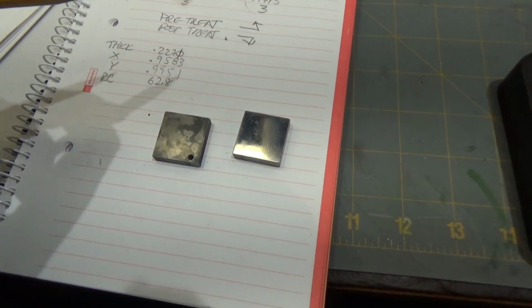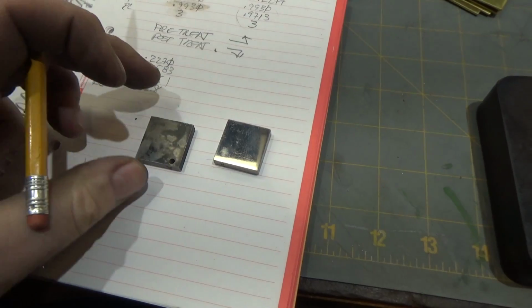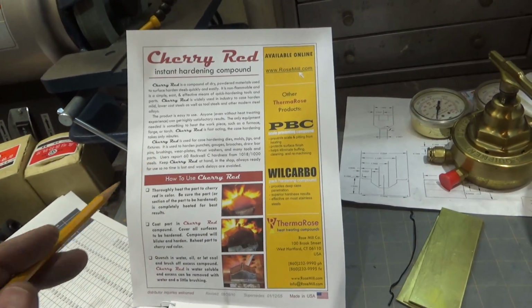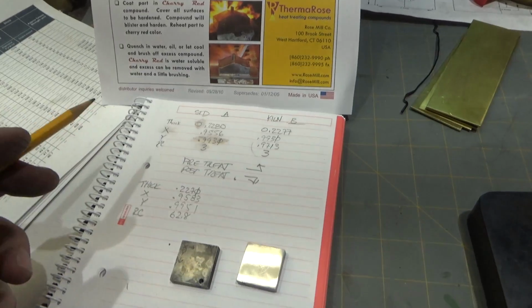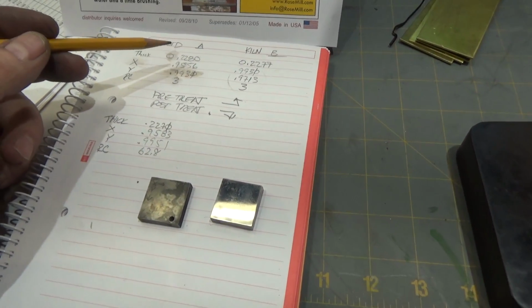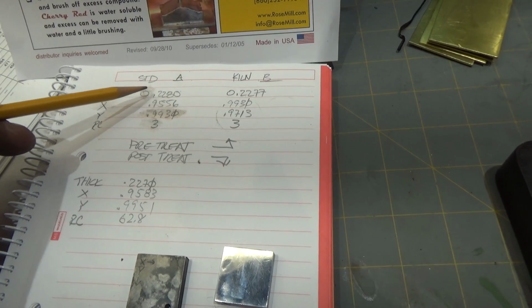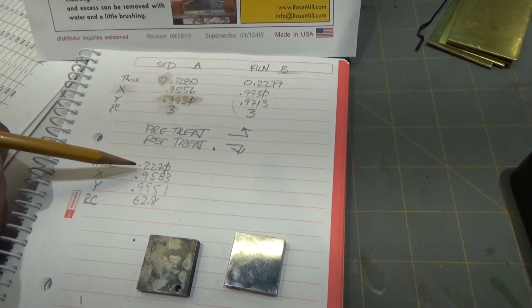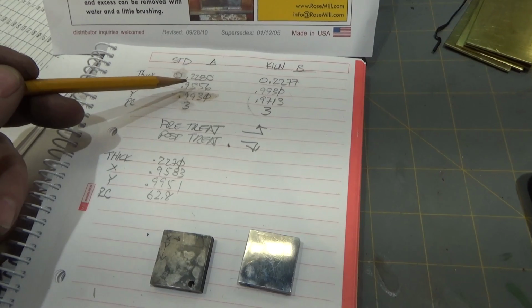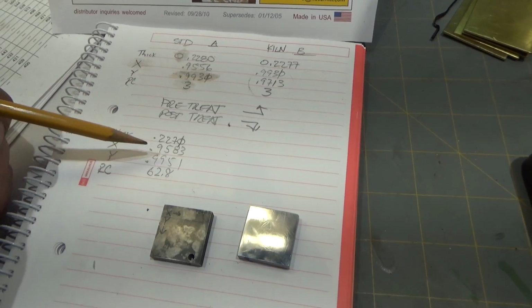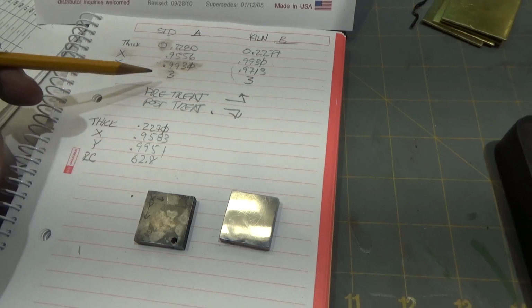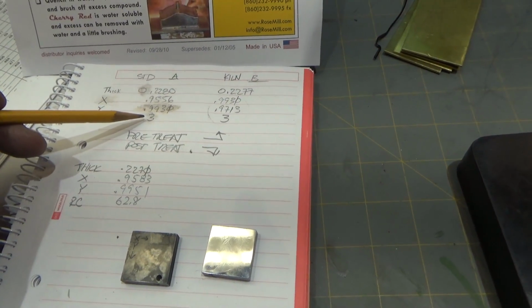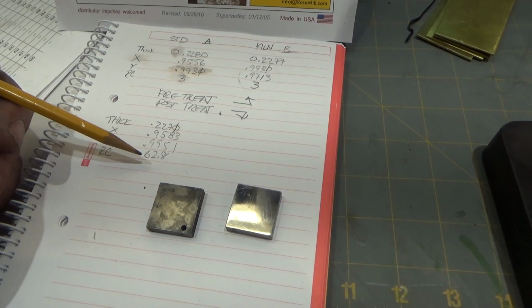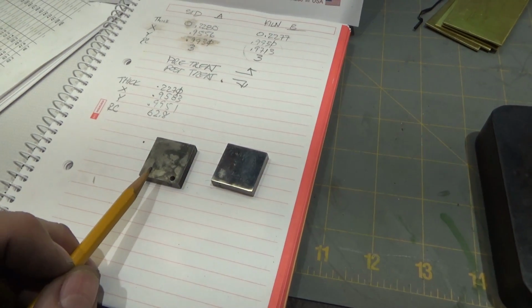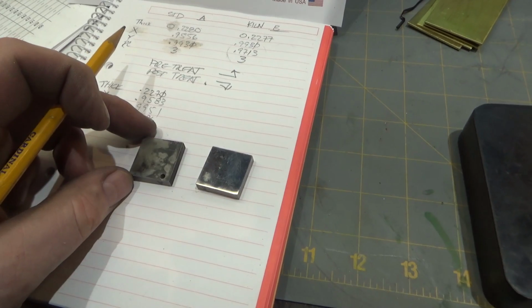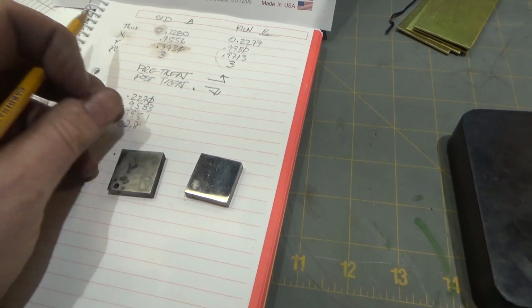So here we are after the first case hardening process, where we followed the standard cherry red process of heating it to red, etc. The dimensions were interesting. The thickness changed from 0.228 to 0.227. The x-axis increased by about 1.5 to 2.5 thousandths. The y-axis increased by 2 thousandths, and the Rockwell hardness went from approximately Rockwell C3 to Rockwell C 62.8. So the depth of the case hardening is probably pretty low.